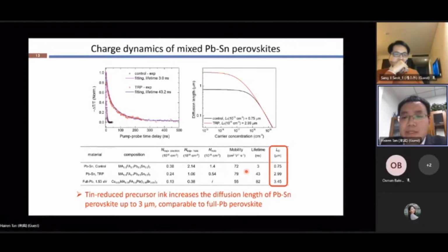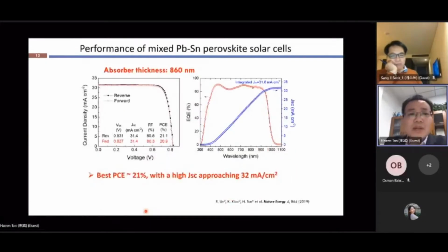As the final result, we can increase the diffusion length of the materials from below 1 micrometer to above 3 micrometers. And this diffusion length is already very comparable to the full lead-based perovskite materials that can give efficiency higher than 24% nowadays. So this means that by using this tin-reduced precursor strategy, we can increase the diffusion length of the perovskite up to 3 micrometers. The benefit of this increased diffusion length is that we can use an even thicker absorber layer, up to almost 900 nanometers, and then we get the best efficiency of around 21%.